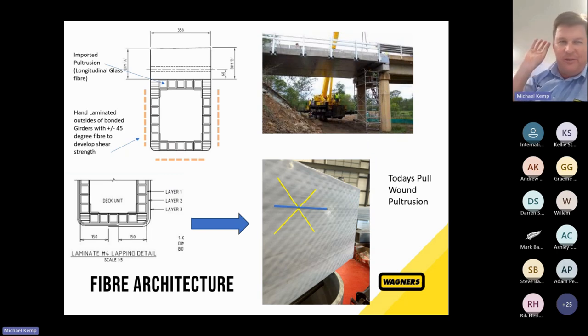Now, the traditional pultrusion, 90% of it is longitudinal fibre. So we would have to hand laminate on the outside of these girders with a plus and minus 45 degree double bias glass fibre, so that we could carry shear loads, which happen at plus and minus 45 degrees. Through some innovation sessions at the time and through frustration from having to do so much hand laminating, we said what we really need to do is to get this double bias glass into our pultrusion. That simple comment led to development of pull winding. So we're one of the largest pull winders in the world, and pull wind some of the largest profiles in the world. You can see today, this is a 250 deep by 100 wide rectangular hollow section. You can see our blue line. I've just marked this up to indicate we've got longitudinal fibre, so still lots of longitudinal fibre, and then plus and minus 45 degree fibre for those shear properties.